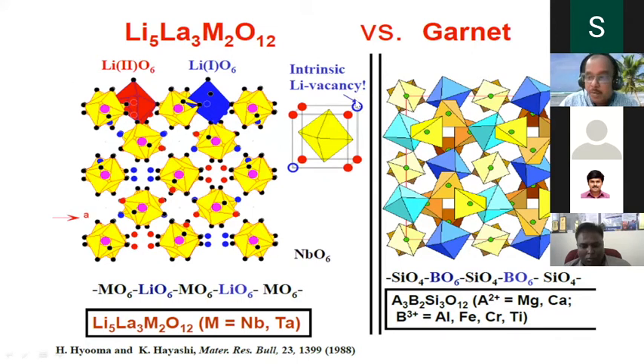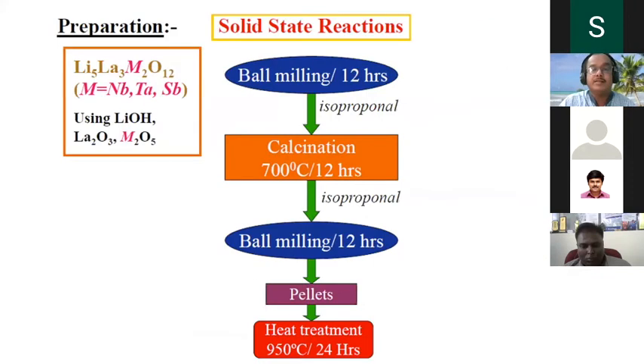What made us interested in this class of system is that people have reported there is a vacancy and it's not completely filled. So, since there is a vacancy, there is every possibility lithium can make a jump into these vacant sites, and there is every possibility we can realize lithium ion conduction in these materials. This is how it started.